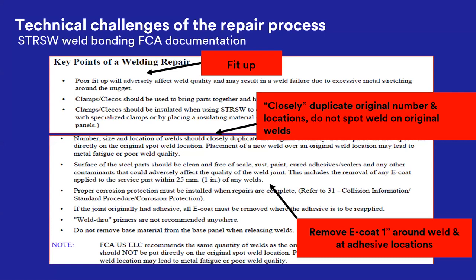So fit up is really important. So we see that some techs kind of develop some bad habits sometimes and get in a little bit of a hurry. And what they do is sometimes they'll start to attach a panel that really doesn't have good tight fit up at the bonding joints. And what happens there is if you're using the welder to pull the panels together as you're welding, when those panels get pulled together under stress, once that weld nugget area gets red hot and softens up, then those panels that are still springy are going to spring apart, and that's what blows a hole in those panels. So it's important to have really good fit up and make sure your panels are dry fit before you attach them. Make sure you don't have any large gaps, there's no tension on the panels, and get that good fit up before you start to bond these panels together.